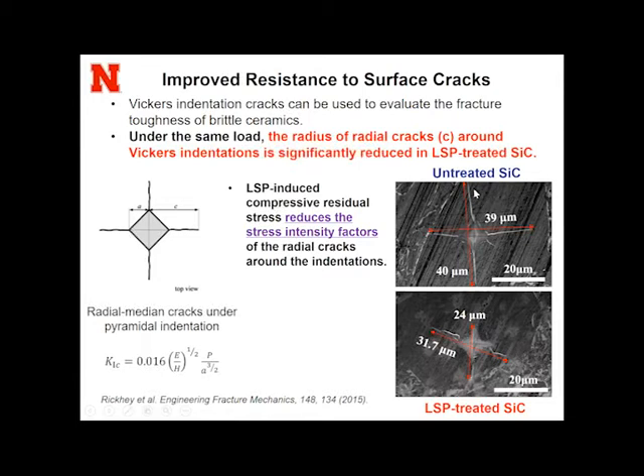Because laser shock peening is a surface effect, for evaluation of the mechanical property, we think Vickers indentation or nanoindentation would be a better method to study than microscale methods such as SENB. In ceramics, the common knowledge is that if you make a Vickers indentation, because ceramic is brittle, it will generate some cracks at the corners. And the crack lengths can be put into an equation to calculate the fracture toughness. So here, we compare the case before laser shock peening and after laser shock peening. You can see the crack length is significantly reduced, which indicates the fracture toughness is enhanced.